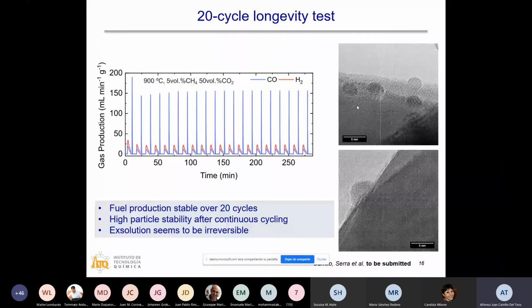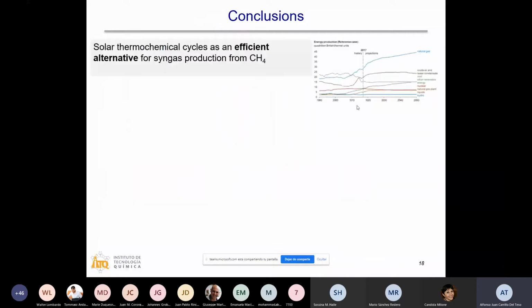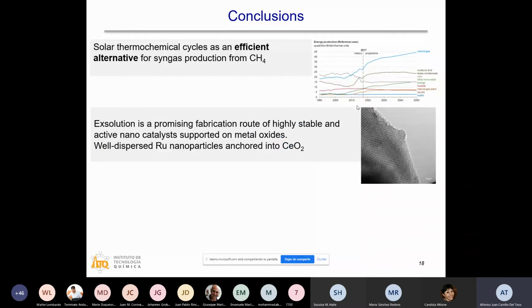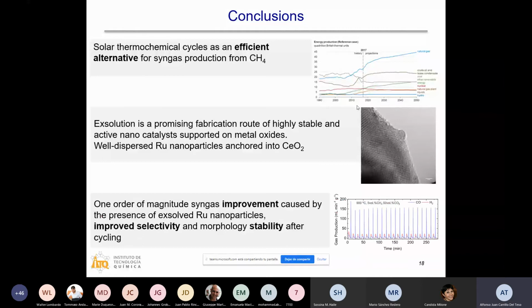So going to the conclusions, I think, although here we are obviously using natural gas, fossil gas, it is maybe an efficient and sustainable alternative to other ways to use methane. And given the projections, this might be interesting. We also demonstrated that we can exsolve ruthenium from cerium oxide with well-dispersed ruthenium nanoparticles. And we also demonstrate that this is quite stable in this 20-cycle test, and the ruthenium nanoparticles remain well attached to the cerium oxide.